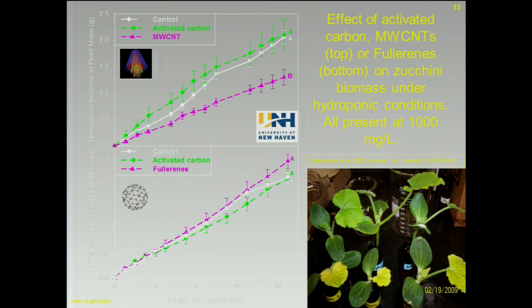This is fullerenes. When we apply fullerenes compared to activated carbon, you observe that fullerenes are performing slightly better than the control. So fullerenes act like a fertilizer. Multi-wall nanotube is more toxic, and there is a speculation why that happens. There have been other results where people have done experiments with tomato and other plants, and they found that, first of all, fullerenes do not have the metallic nanoparticles that multi-wall carbon nanotube has. So the effect you are observing here is not only from the multi-wall carbon nanotube, but also from those metallic catalyst particles.